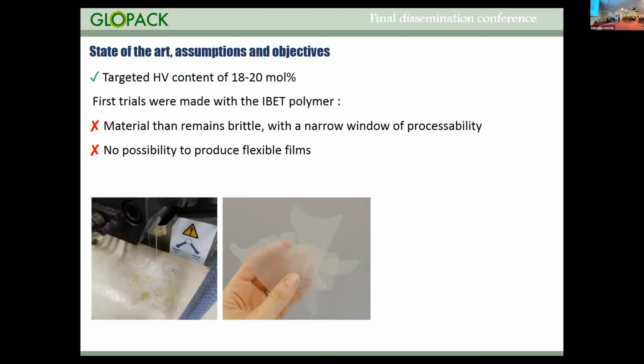As presented in the previous presentation, we managed in the project to produce polymers with HV content between 18 and 20%, but also an HV content of 30%. And at the beginning of the project, first trials were made with these high HV polymers. And unfortunately, we see that the materials remained brittle with a narrow window of processability. So we had difficulties to produce sheets especially, and there was no possibility to produce flexible films.